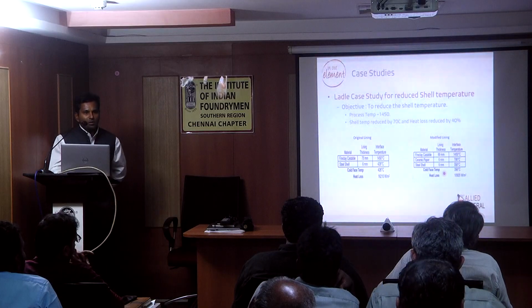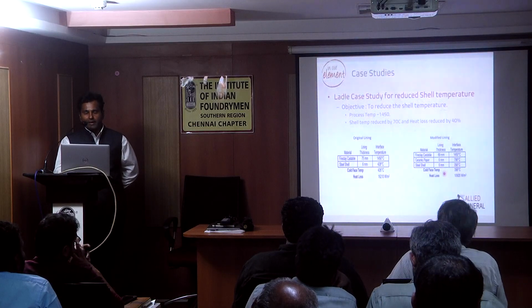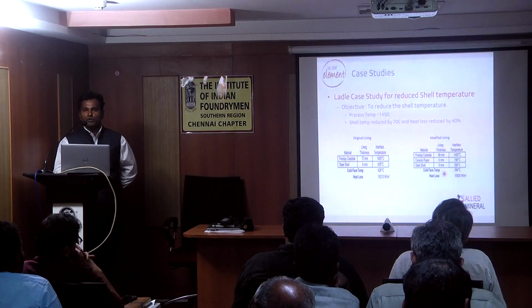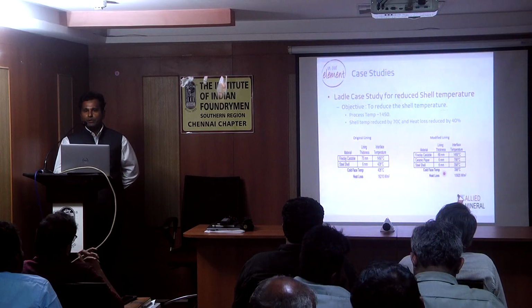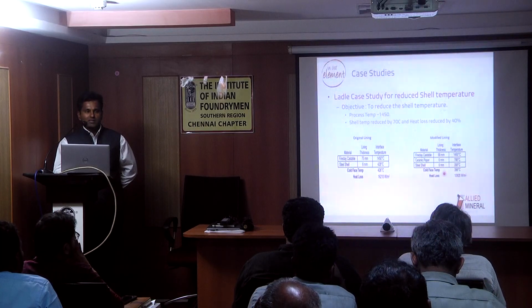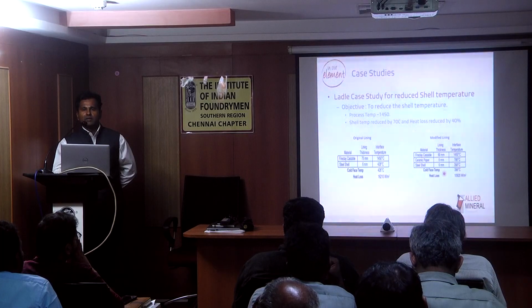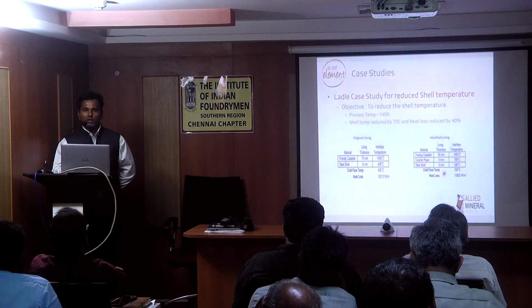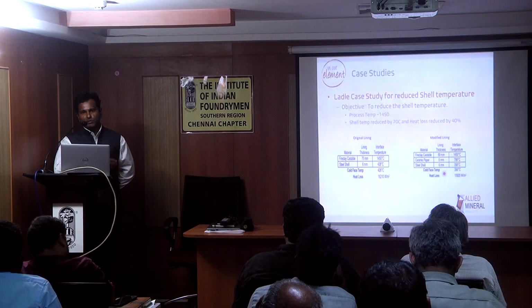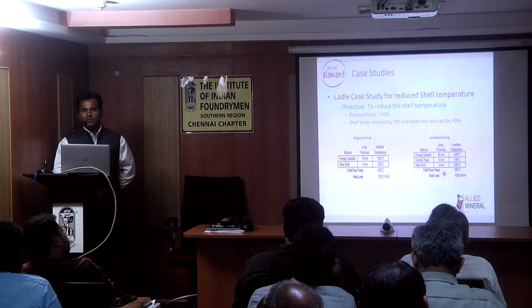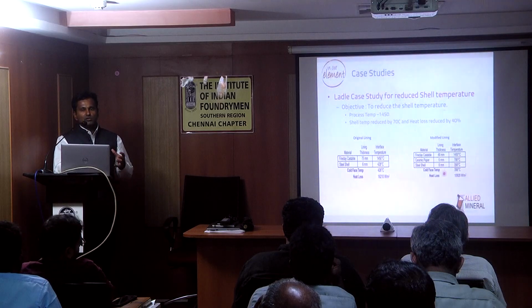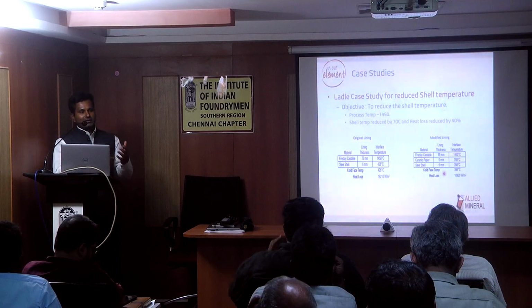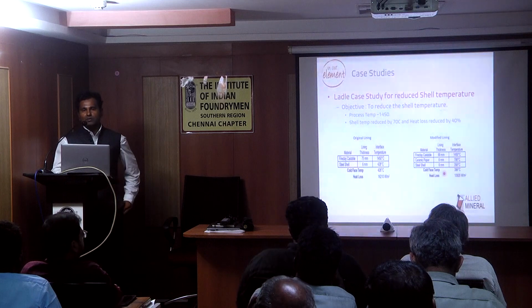During our visit, one of our foundries also emphasized this introduction of CF paper. Earlier they used a castable without the CF paper. They were losing the heat very fast and had to reheat the ladle in subsequent heats. But after introducing the CF paper, the heat containment was more, so they don't need to heat the ladle for further heats. The heat was retained well.